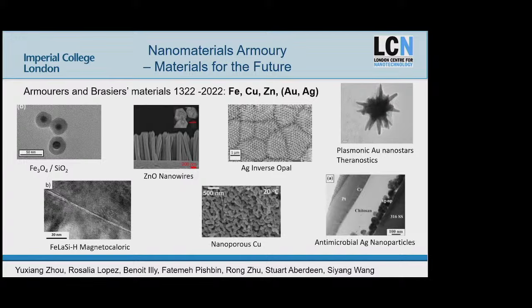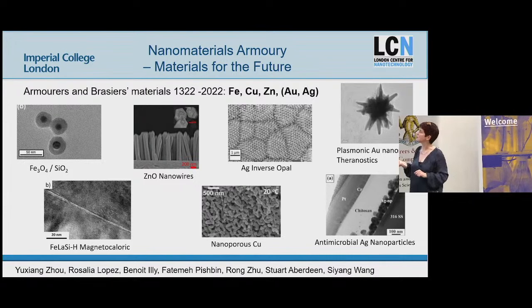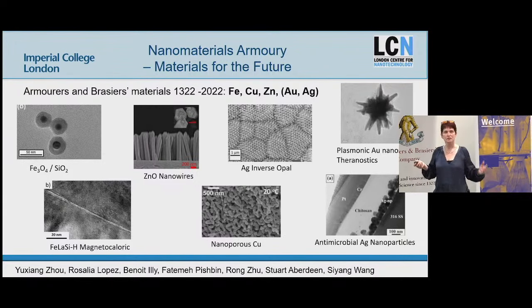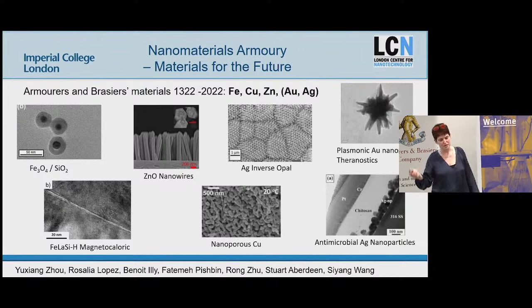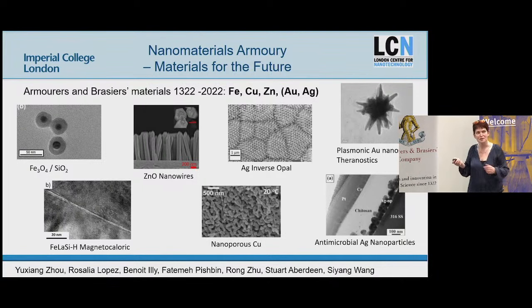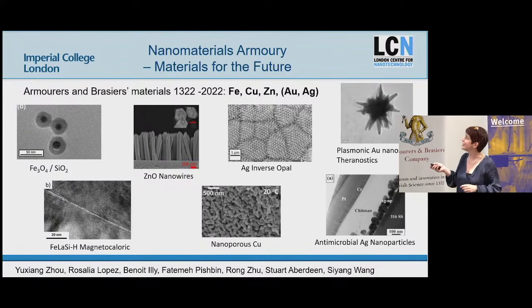So thinking about iron oxide and zinc oxide, and I didn't talk too much about this. This is a super cool material, lanthanum, iron, silicon, magnetocaloric materials, where the interface in these materials is critical for controlling the properties for refrigeration. Nanoporous copper for CO2 reduction, potentially. Stars and opals for a sustainable future. It is a material world, right? And we need to use materials carefully, and we need to design them for careful use, like the armorers and braziers have been doing for 700 years.